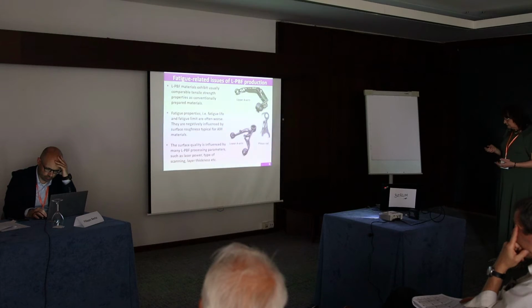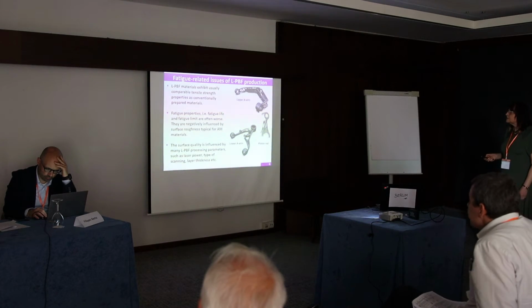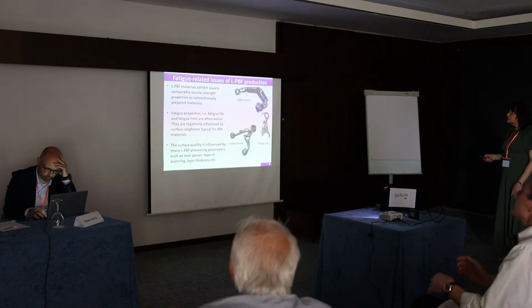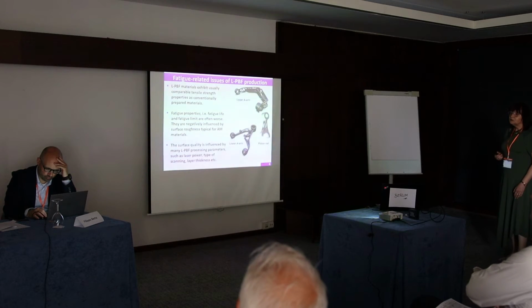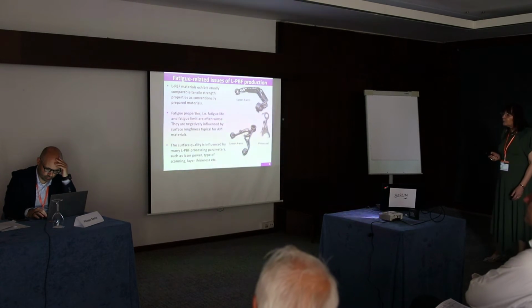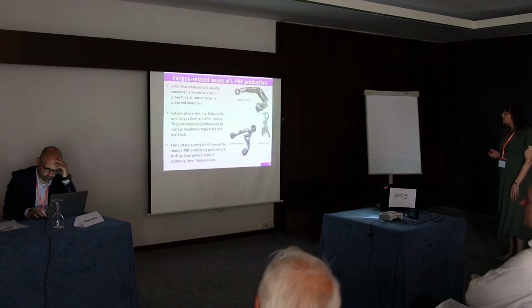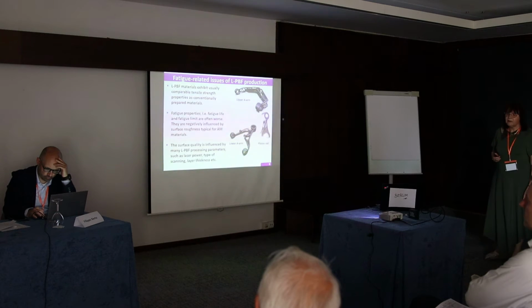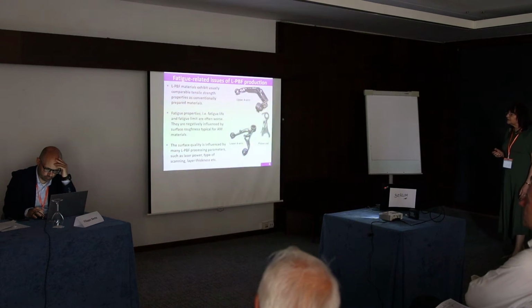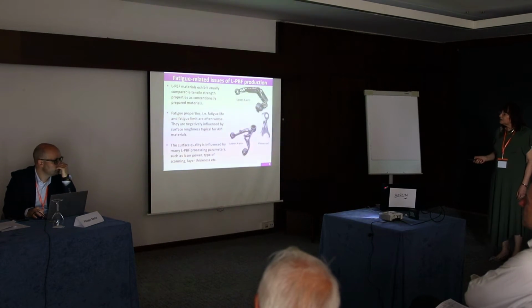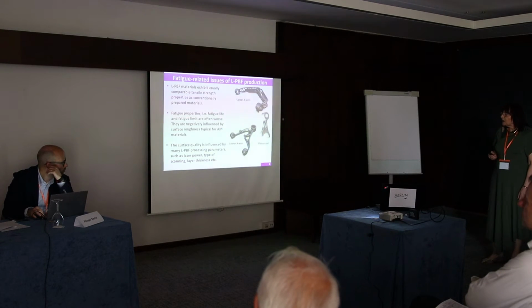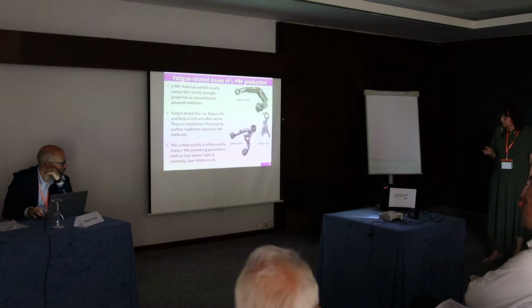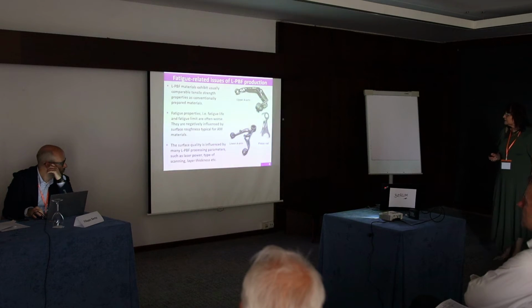The fatigue-related issue is that laser powder bed fusion materials usually exhibit tensile strength comparable to conventionally prepared material, but fatigue properties, that is fatigue life and fatigue limit, are often worse, and they are negatively influenced by the surface roughness typical for additive manufacturing materials.